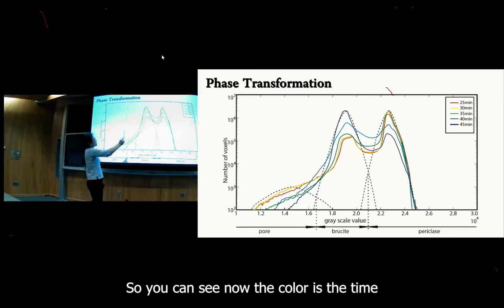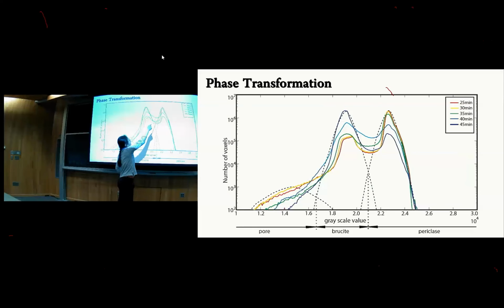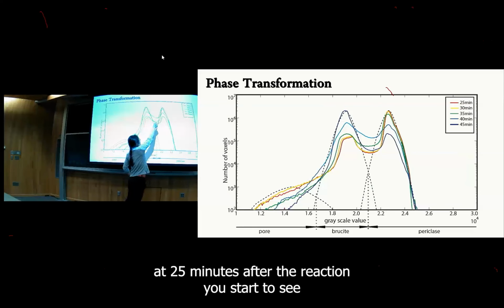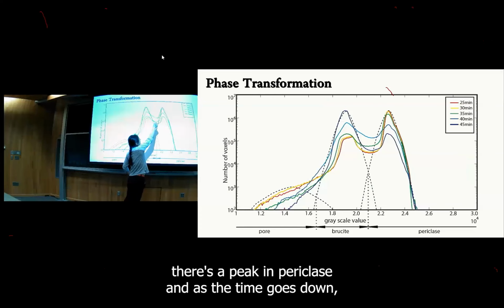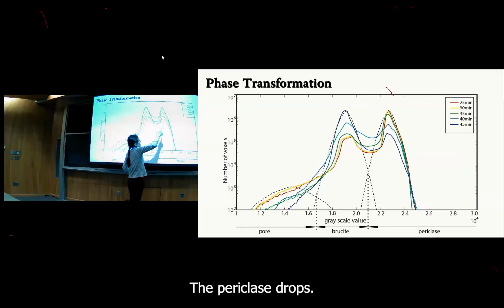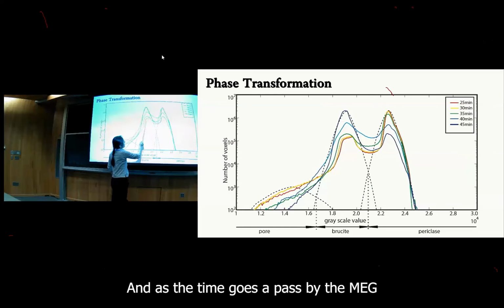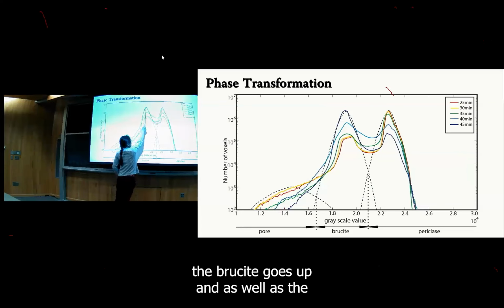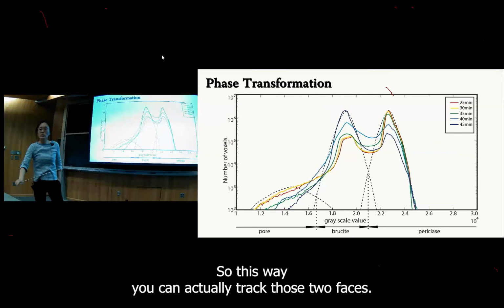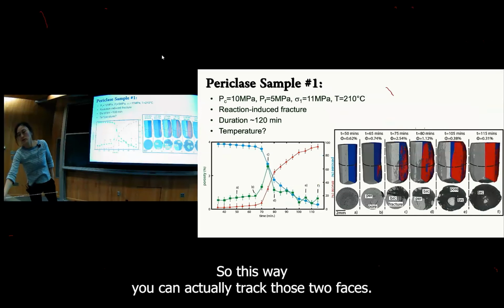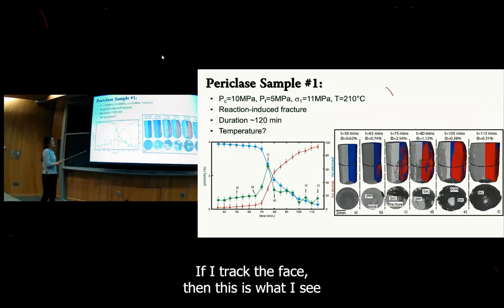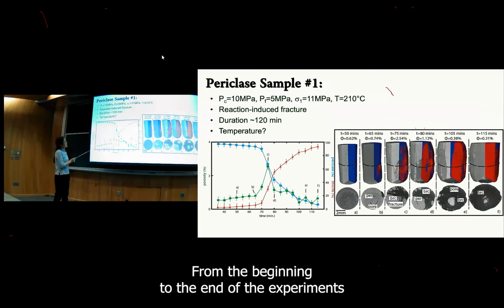So you can see now the color is the time. At 25 minutes after the reaction, you start to see a peak in periclase. And as time goes on, the periclase drops, and as time goes by, the brucite goes up, as well as the void. So this way, you can actually track those phases. If I track the phases, this is what I see from the beginning to the end of the experiment.